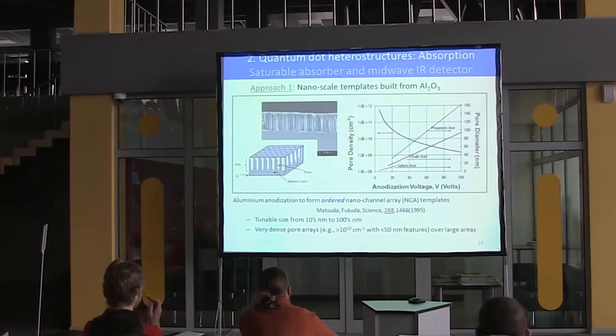Those can be used as templates, which I can stick on top of a substrate. This is done in alumina. We did it in alumina. And here's a gallium arsenide substrate beneath, Van der Waals bonded. And you can see we've taken a section, so you're looking through the pores just like in this picture here.